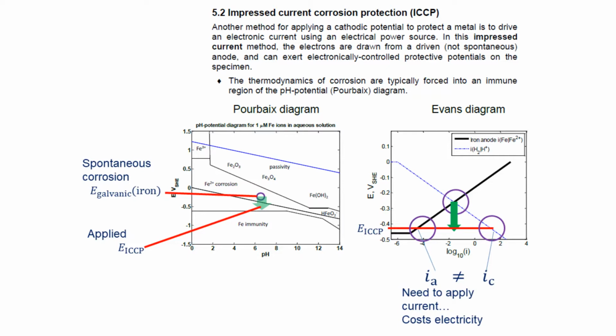Now, suppose we can do that. We now find on the Evans diagram that we have a lower surface potential, which means that when we look up the current densities for the two processes, we see that the corrosion current density for the iron has decreased by a couple of orders of magnitude. So that's excellent. The iron is now going to be actively corroding, but barely, only at a very slow rate.